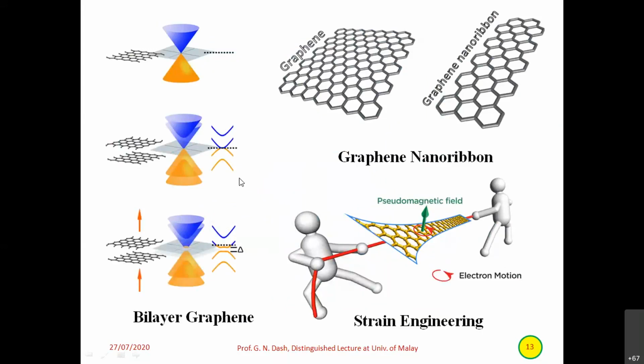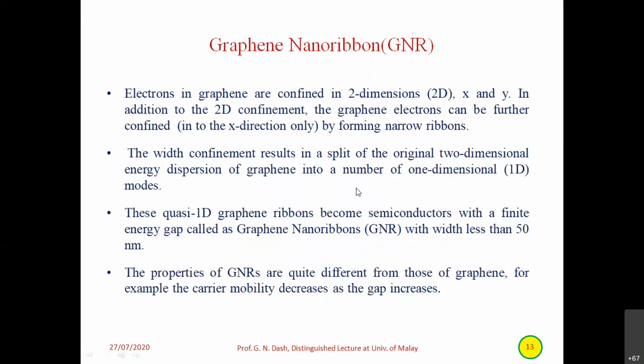It has been illustrated here in this slide. This is bilayer, so it has some gap, but this has no gap. Then graphene nanoribbon, you can see this is the picture of the nanoribbon, and this is the strain. And it's a pseudomagnetic field. It stretches the graphene, and therefore it develops some band gap. Now, what is that graphene nanoribbon? GNR.